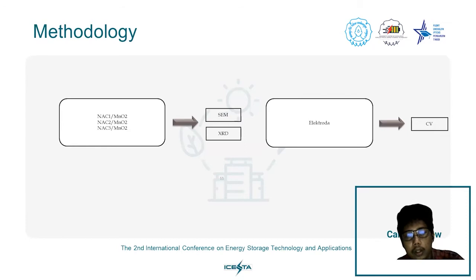And then for the electrochemical performance testing, for the powder of mixed NaC1 MnO2, we test it with scanning electron microscope and XRD. And then for the nickel foam that we got before, we use 3-electrode cyclic voltammetry for the electrochemical performance.